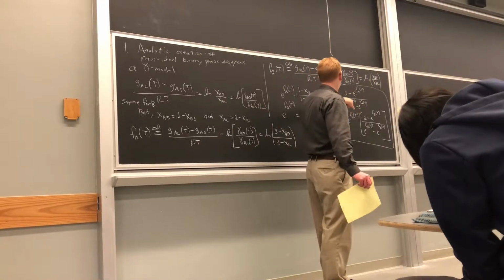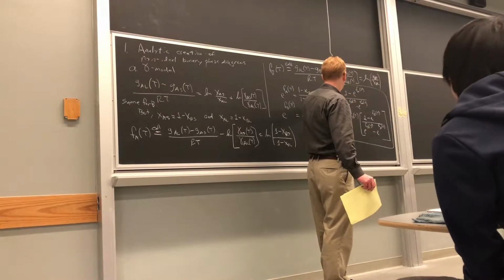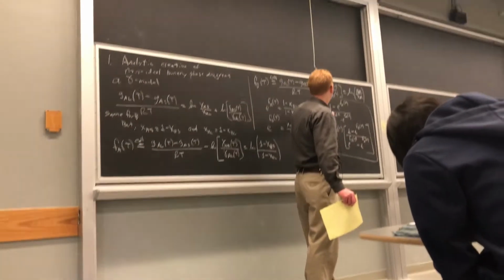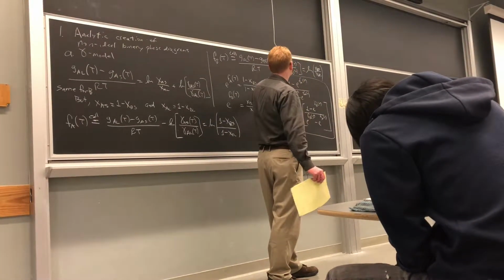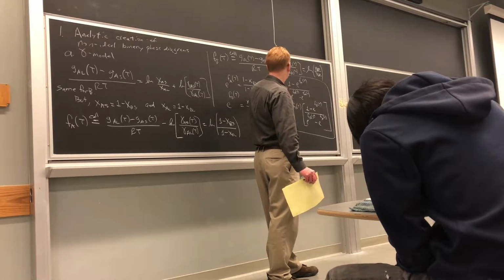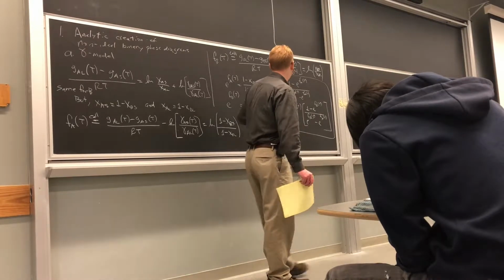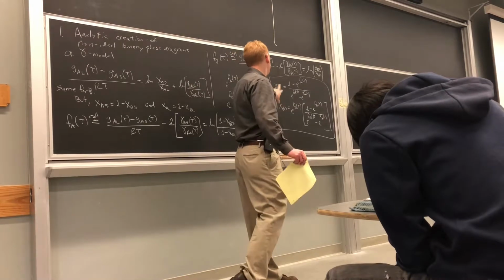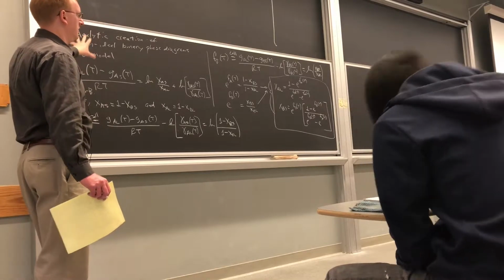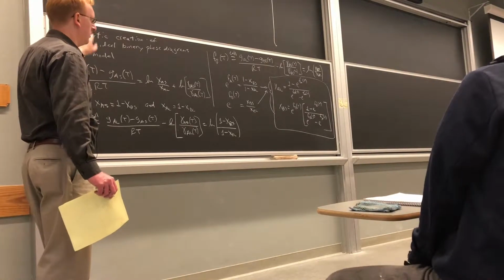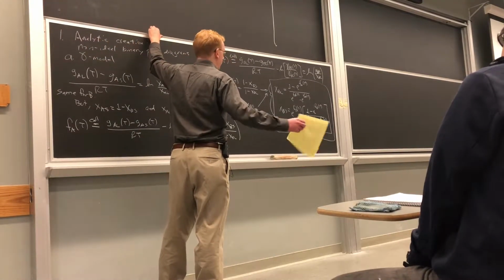And now we've got an equation that relates composition, now this is in terms of B, but composition of the binary solution as a function of temperature, or if you could flip this around, temperature as a function of composition. But either way, this one gives you the liquidus, because this is the fraction of B in the liquid, and this gives you the solidus, the fraction of B in the solid. And these are for the liquidus and solidus because they were derived from the initial condition that mu of the liquid equaled mu of the solid. The chemical potentials of the two phases were equal, which is the criterion for two-phase equilibrium.